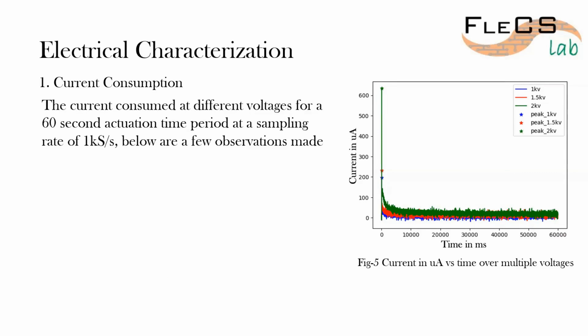The power supply that we were using has a current output monitor at something like 8 hertz, and that's not enough at all to sample when you're charging a capacitor. So the way we did it is we put a series resistance in, and then you have to do a lot of juggling, because there is an isolation circuit and everything else to measure the voltage across it, because you're working at 2 kilovolts and you don't want to fry your laptop. But once you're able to do all of that, you can measure it at something like 1 kilo samples or even 20 or 100 kilo samples. If you do that, you'll figure out that it's just a capacitance charging curve.